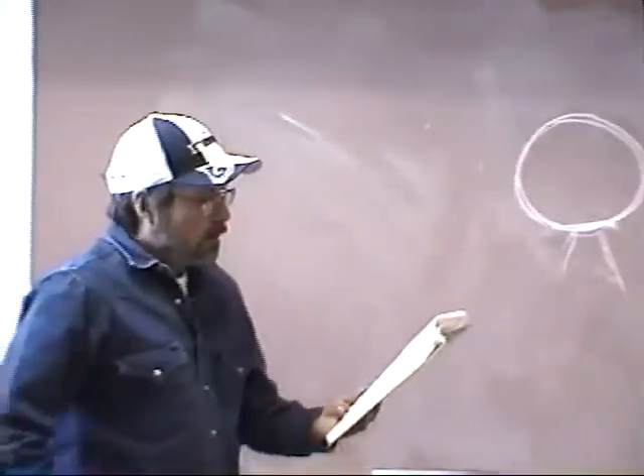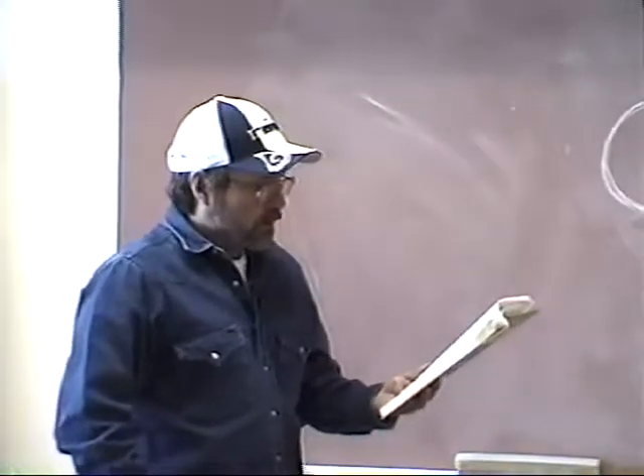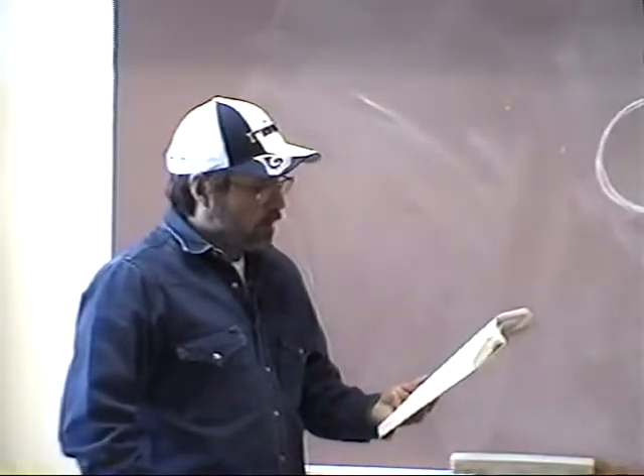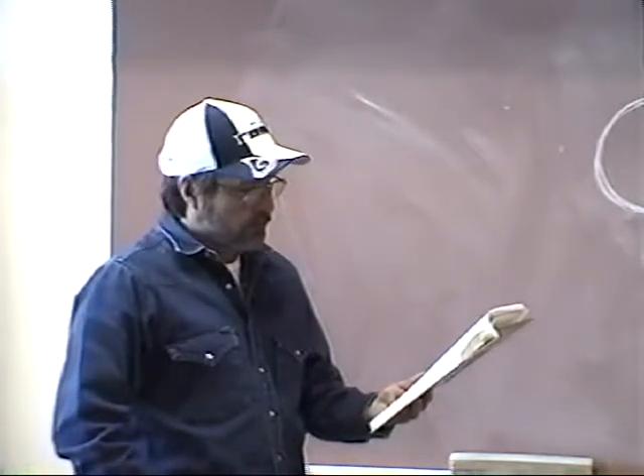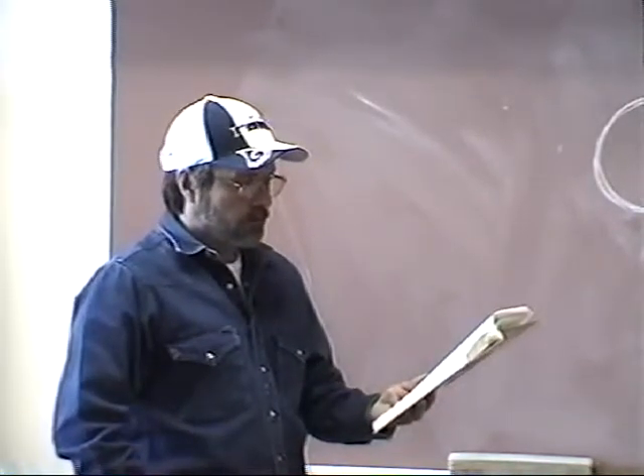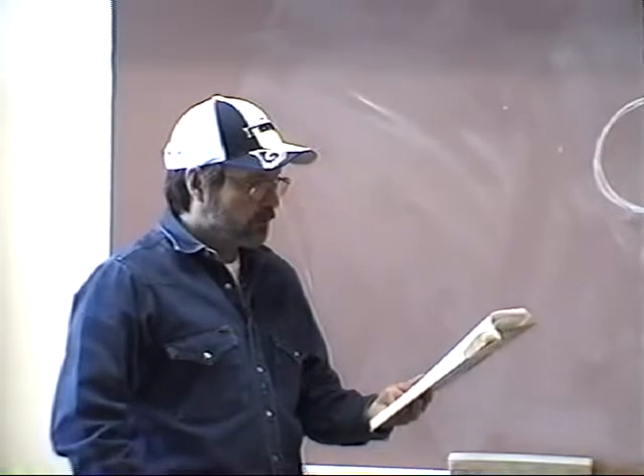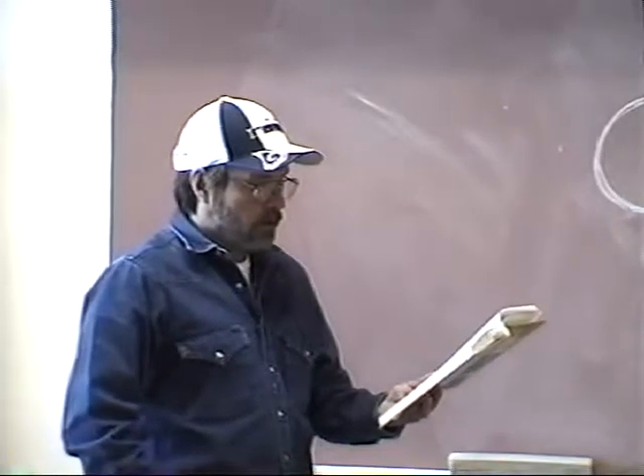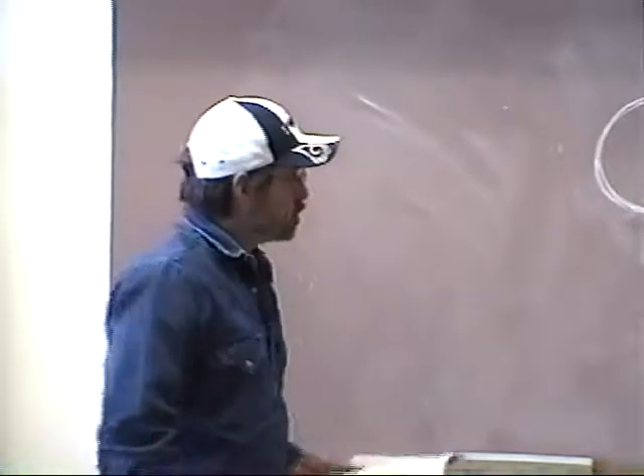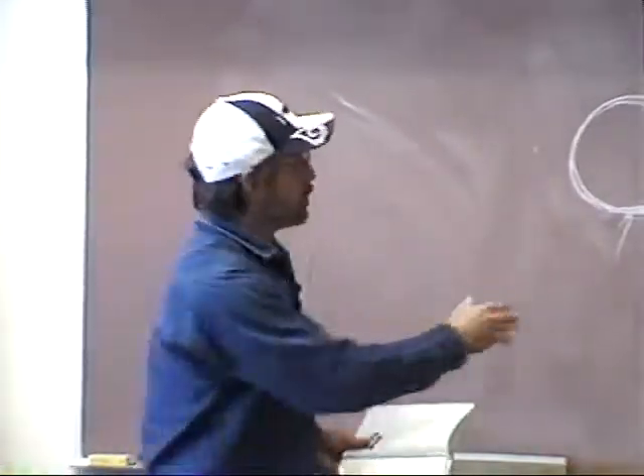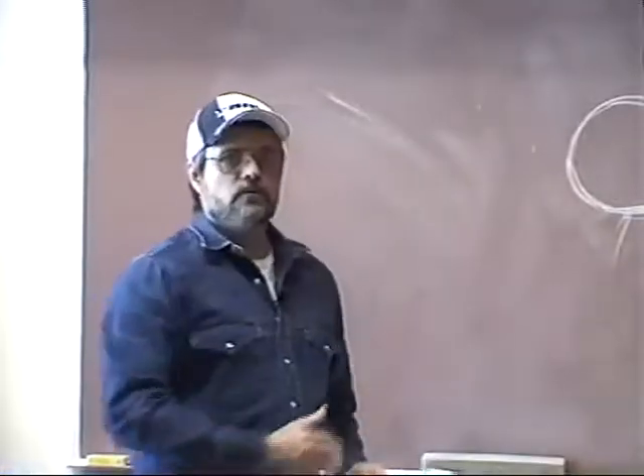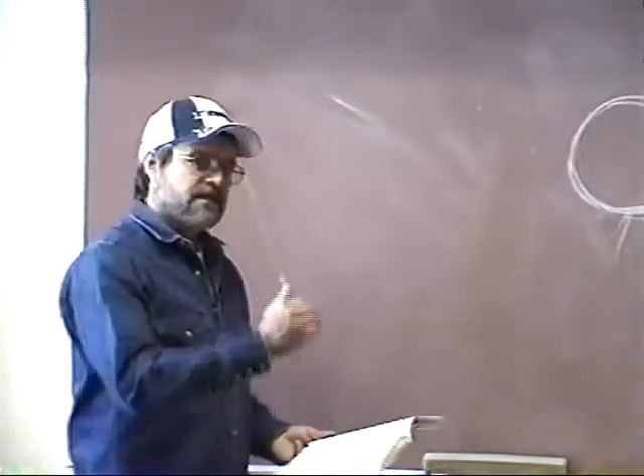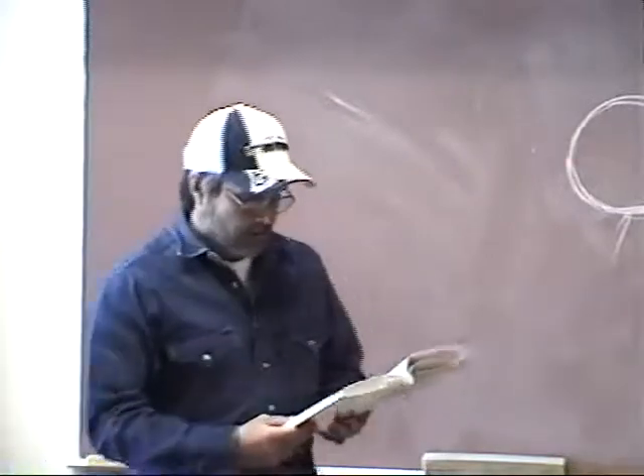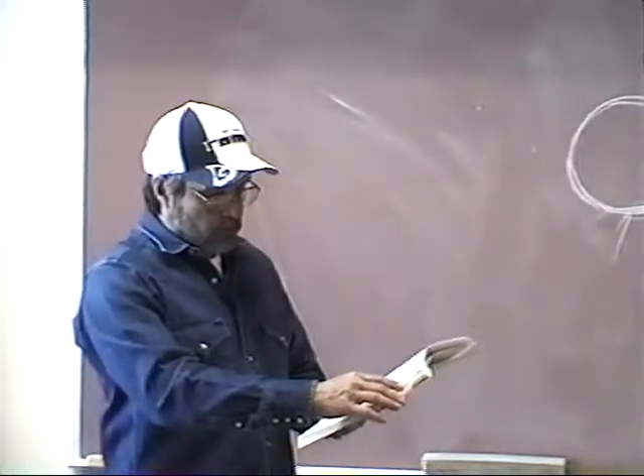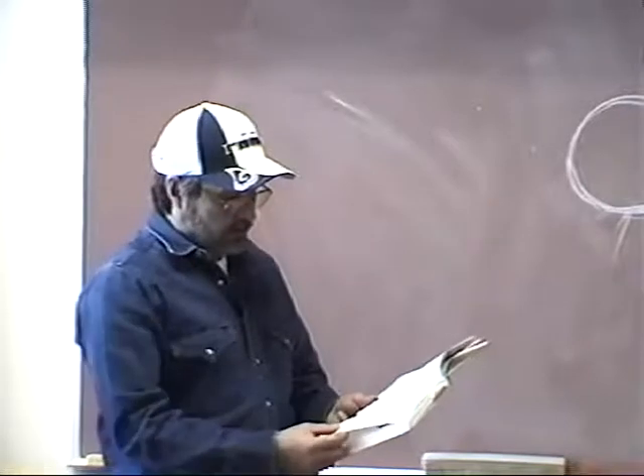Okay, the keyhole, page 27. The keyhole is an essential part in welding a root bead. It should be about 1 1/3 times the diameter of the electrode. The keyhole helps to ensure that the deposited bead will penetrate to the root, as evidenced by the small crown at the back of the bead. You should have about a 1/16 to a 1/8 crown, or inside reinforcement. They call it root reinforcement, on the inside of the pipe. That's the ideal. This crown should rise about 1/16 inch above the inside surface of the pipe.